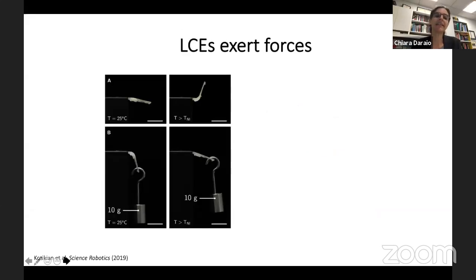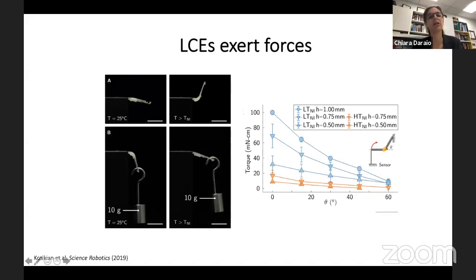So these LCE hinges can also exert forces, and we measure that a bit like a weightlifter, straightening the hinge and letting the hinge lift different weights for a large number of cycles. And you can see, for example, the torque applied as a function of the bending angle in these measured values.